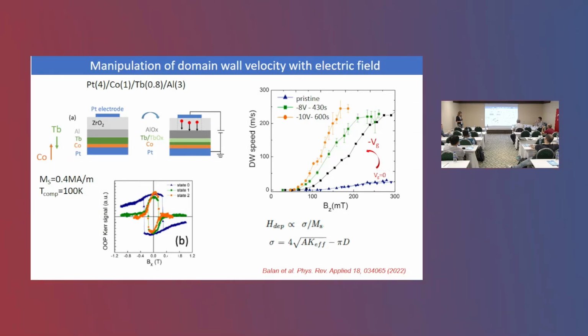When we apply the gating, that pushes oxygen ions towards the interface, towards the magnetic layer. What you observe by Kerr microscopy is, first of all, that below the electrodes we have a decrease of the in-plane saturation field. In the domain wall velocity, you can see that by increasing the gating, we have a decrease of the depinning field, and then eventually the recovery of the high domain wall velocities, those that we expect for systems with high DMI and chiral Néel walls.